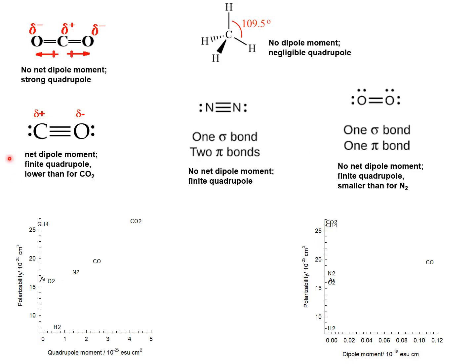Let us examine the key properties such as polarizability, dipole moment, and quadrupole moments of guest molecules such as carbon dioxide, methane, carbon monoxide, nitrogen, and oxygen. Here I plot the polarizability versus the quadrupole moment, and we note that the polarizability of methane is practically the same as that for carbon dioxide, but carbon dioxide has a significantly higher quadrupole moment.